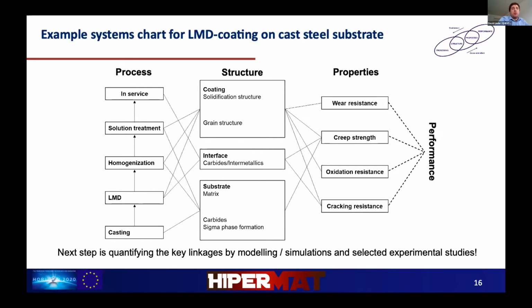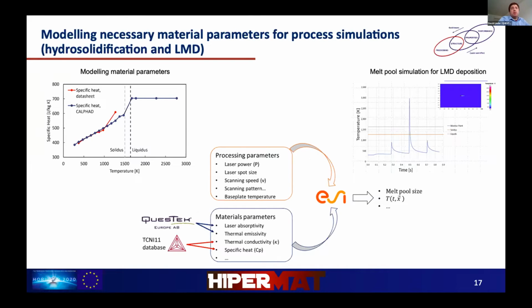So the next steps that we're working towards is to quantify these key linkages by modeling, process simulations, and selected experimental studies moving along the project. And here is an example of how we are combining material modeling and process simulations that are performed at ESI by generating material parameters for simulations for the LMD process, for example, also the hydrosolidification process. The example here is for specific heat as a function of temperature, where we can see that using modeling, we can extend upon the ranges available in literature or in data sheets, and enable more reliable simulations of this new process.